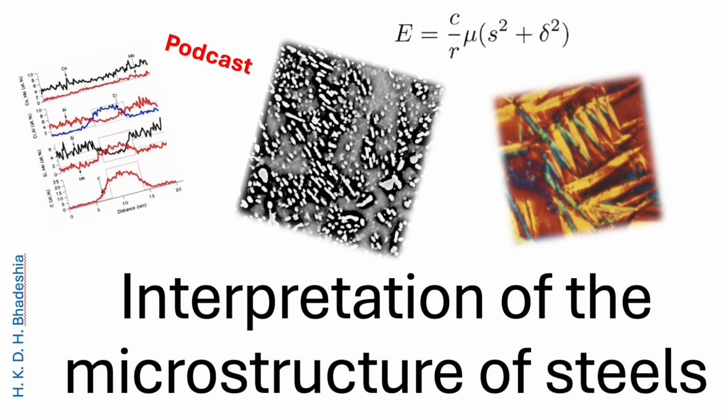Okay, here's where it gets really interesting for me. Pearlite. When you look at a micrograph, it looks deceptively simple, right? Like these alternating layers. But what is it in 3 dimensions? Pearlite is a mixture of ferrite and cementite. It forms by cooperative growth, where both phases grow at the same time at a single front with the austenite. Now, your 2D cross-section looks like layers, but in 3D, the structure is actually an interpenetrating bicrystal. And interpenetrating bicrystal, yeah, the cabbage and water analogy is probably the best way to visualize it.